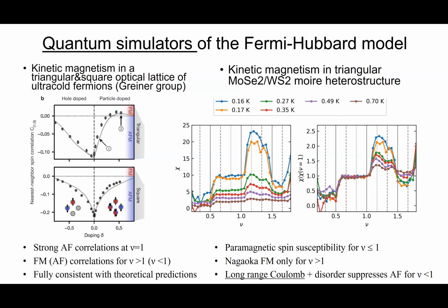But the ideal scenario would be that if you tune it further out, and this doesn't seem to be possible, that is after you have nu equals 1, right after you fill these deep Moire potentials with one electron, then due to the Hartree Moire effect, the fact that the band is now a lot more dispersive, and you bring the tungsten band closer in energy, that you could actually put electrons into the dispersive tungsten band, and then you have the Kondo lattice model. It didn't work.